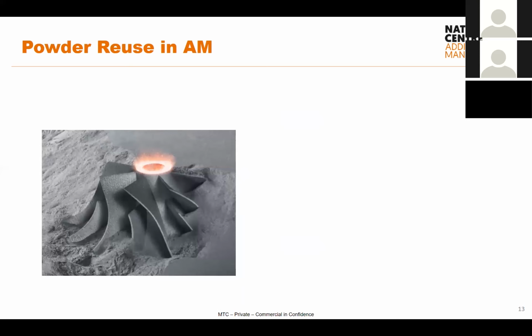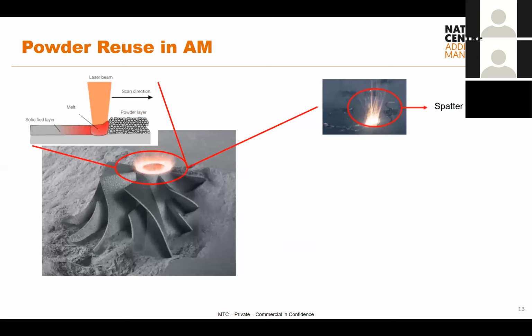So on to powder reuse then. Why is this so important? In the process, there are several things that we want to be concerned about. The first one is a phenomenon known as spatter, weld spatter. I already mentioned that powder beds themselves are very poor conductors of heat. So what this means is that when we melt the powder particles during the process, because we're not releasing that heat from the melt pool, the melt pool can exceed the boiling point of the material. And if that were to happen, we get this, where effectively we get particles ejected from this melt pool.